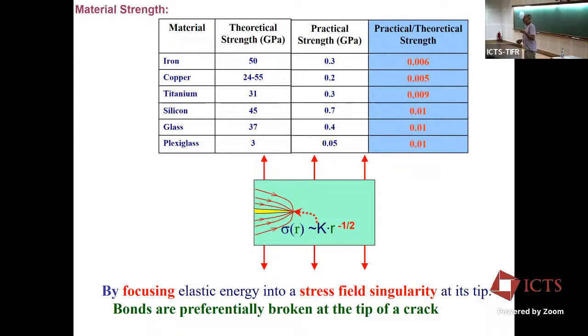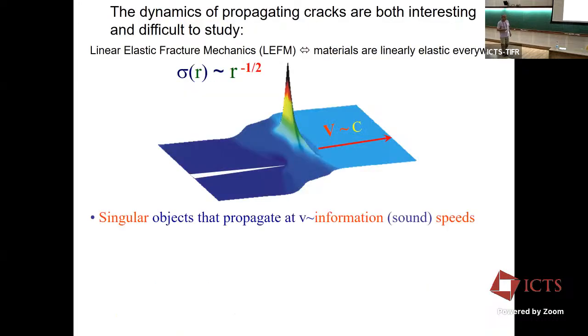With a 1 millimeter diameter glass fiber, you can lift a grand piano. It's strong enough. You can actually do that if you make fused fibers with 0 defects and you acid coat them to get rid of all the little cracks on their edges. You can lift incredible weights. Personally, I wouldn't stand underneath that grand piano though, but if you're very, very, very careful, you can approach the theoretical strength of a material, but it's almost impossible, as an experimentalist at least. Okay, so the cracks focus this elastic energy into this stress field singularity and preferentially break bonds. And that's why we get this huge reduction in material strength.